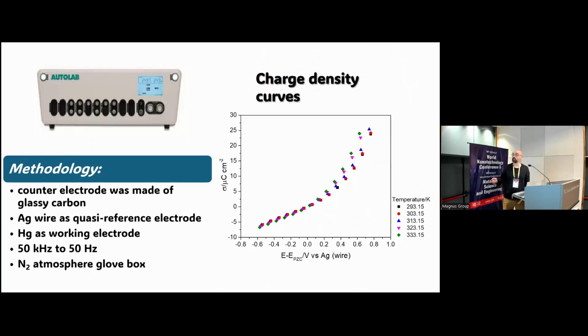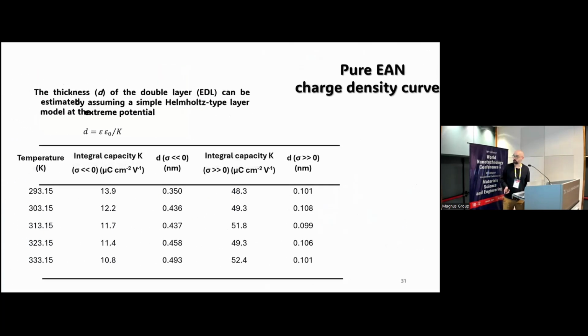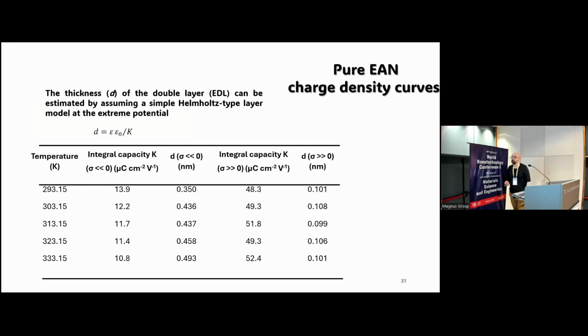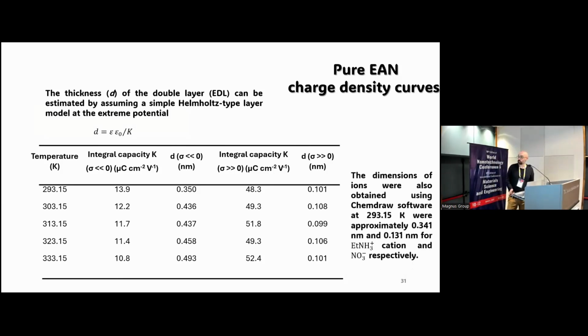You can also see here the charge density curves, that is the integration of our previous slide. And this is remarking the ability to store energy of our compound. Using a simple Helmholtz type layer model at the extreme potential, it's possible to determine the thickness of the double layer, this layer that is subsequent to the electrode. And if we compare this with Chemdraw software, you can see that at room temperature we have quite good similar values between simulated and experimentally obtained.